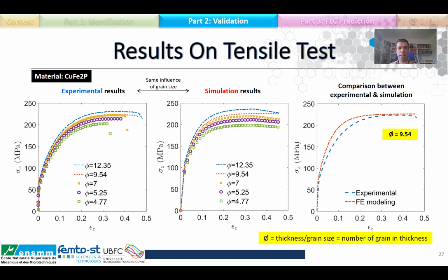The first validation test we try with the parameters identified by micro-indent is simply a tensile test, but on a different grain size. The quasi-static tensile test is performed with an electromechanical MTS machine. The strain measurement is done by a laser extensometer and digital image correlation. To ensure repeatability, each test was repeated 3 times for the same grain size.